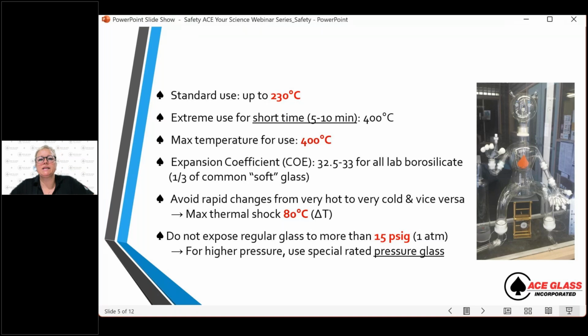Our standard borosilicate glass has an expansion coefficient of 32.5 roughly, up to 33, which is about a third of common soft glass, which is like drinking glasses, which basically just means it expands and contracts slower than your standard drinkware, for example. Generally, you should avoid rapid changes from very cold to very hot and vice versa. I know they say, oh, Pyrex, you can do this. But really, the maximal thermal shock that you should expose your glassware to shouldn't be more than 80 degrees Celsius. That is basically if I have very cold glassware and I pour boiling water in it, or any kind of heat, make sure the thermal shock is no greater than 80 degrees Celsius.